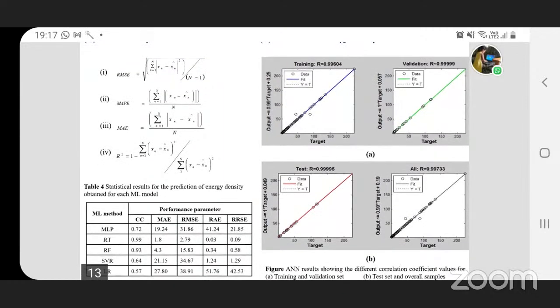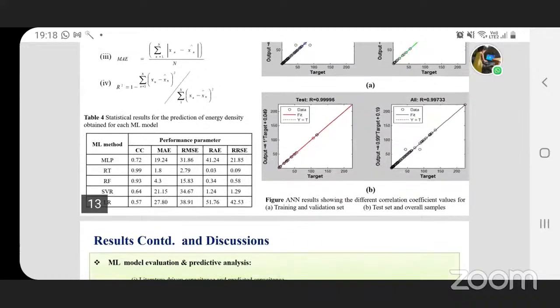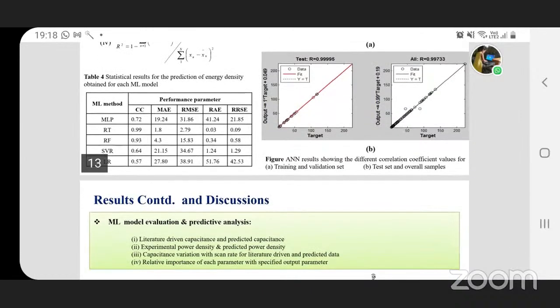Again, we considered our designed NN model as well as the different ML methods, and we found that for the training, validation, test, and overall samples, the value of correlation coefficient was 0.99, which was again providing a very good fit of the experimental as well as the predicted values. And we have tabulated the error performance parameters. Again, we found that the values of correlation coefficient for random tree and random forest were very high, nearly equal to 1. And the root mean square values for those two methods were really very low.